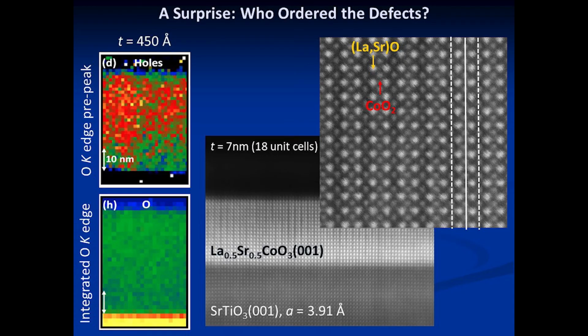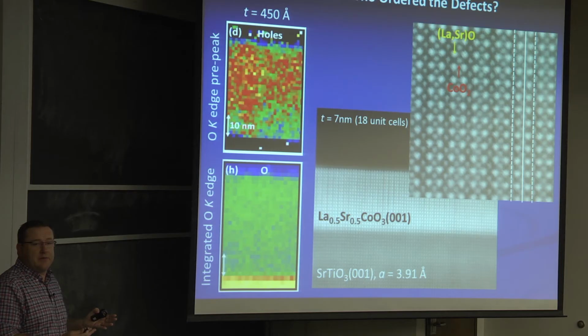Okay? And it did not take us very long to figure out what was going on here, because we put the electron beam on the dark stripe, we measured the oxygen content, much less than 3, and then we put it on the bright stripe, and it's exactly 3. So we discovered something really pretty amazing. The oxygen vacancies, you tend to think of those things as being random. In this material, they're not random. They line up into stripes, and those stripes run in a very specific direction, right?